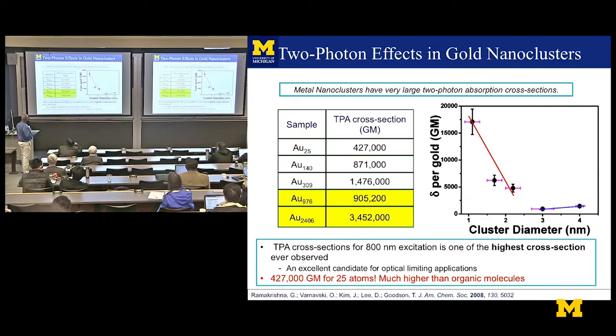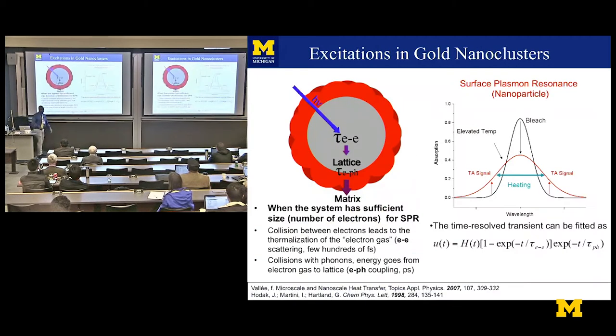So if you look at the cross-sections of these structures, and then you look at it from per gold atom, you can see that there's some kind of enhancement that happens because gold 25 really should not have had such a large cross-section. What's going on? Then, as I mentioned before, we've worked with several laboratories, like the DoD laboratories and so on, and they became very excited, and of course they investigated these properties of these gold clusters as well and found this very large cross-section. And they wanted to understand why. Well, one way you can try to understand why is to see exactly what's happening to the cluster, the crystal structure, if you will, of a single cluster, if you will, when you excite it with photons.